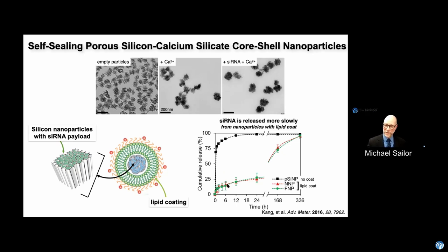You can see the data here on the right, the green and red dots. There's one that we call a fusogenic nanoparticle, which I'll talk about in a minute, and one that's a kind of control nanoparticle. Both the red and the green dots have this lipid coating around them. What is it telling you? When you wax your car, it doesn't rust. So if we wrap our liposome around this nanoparticle, it slows down its rate of dissolution. And inside that nanoparticle, the nucleic acid is being protected. So that nucleic acid stays intact, doesn't fall apart, and doesn't dissolve out into solution for quite some time if we wrap that lipid coating around the nanoparticle.